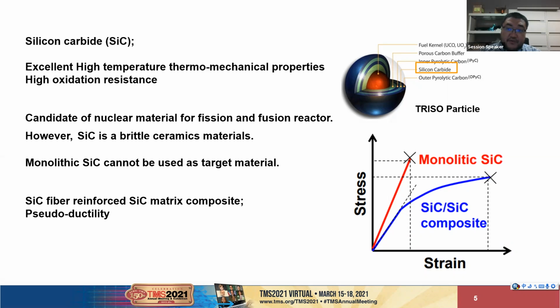And this figure shows the structure of a typical TRISO particle. As you can see, one shell of the TRISO particle is made of silicon carbide. However, the monolithic and pure silicon carbide is very fragile and easy to break. And its brittleness limits its use as a structural material.